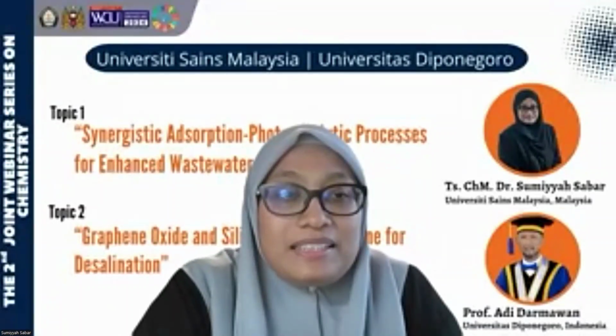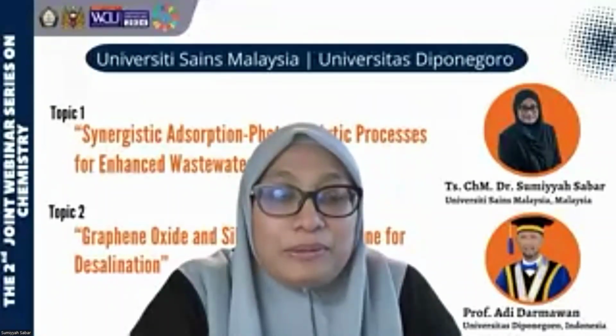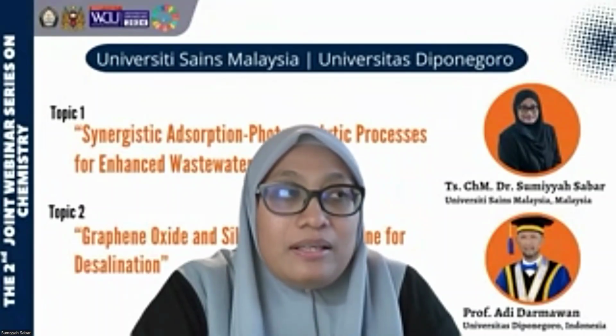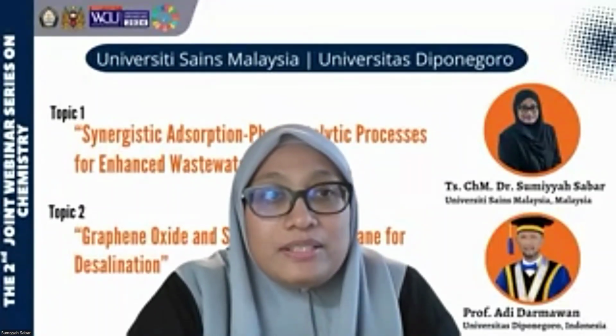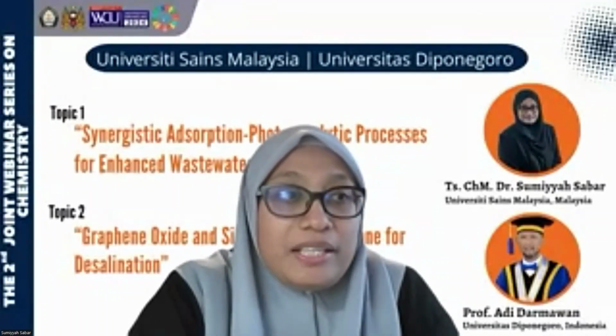Okay, so the band gap energy is very important for photocatalytic study because the aim is to improve the visible light activity of the photocatalyst. When we first did the titanium dioxide chitosan without any dye, and we used phenol as the pollutant, we observed that the chitosan itself was also oxidized, forming carbonyl groups. With the presence of the carbonyl group, it increased the visible light activity of the photocatalyst. So I actually shared the band gap energy. When the chitosan was oxidized, the band gap energy reduced to 2.93 electron volt.